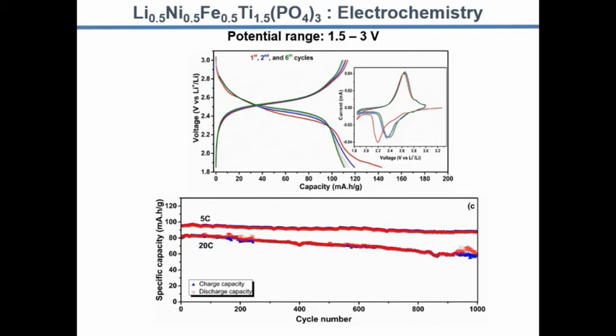We do the same thing during 1000 cycles, and you can see for two regimes, 5C and 20C, we have in blue the charge capacity, and in red the discharge capacity. We have very, very good efficiency of the charge and discharge. We have the same capacity during charge and discharge during 1000 cycles, even at very fast cycling. Very fast means very high, very powerful current during 1000 cycles of charge and discharge. This is really very short, briefly the results obtained, but we can check in the paper more details about the studies.